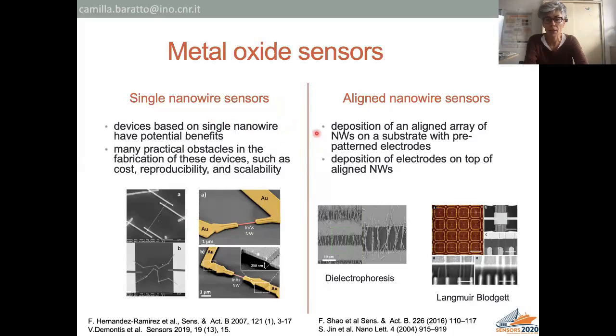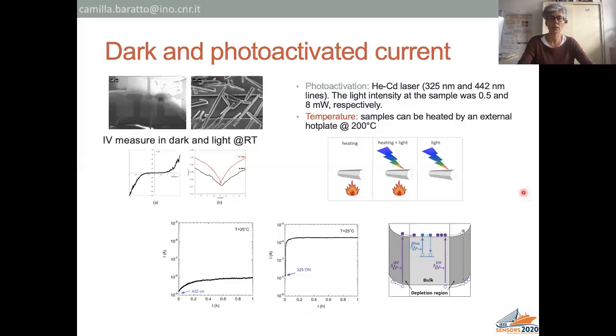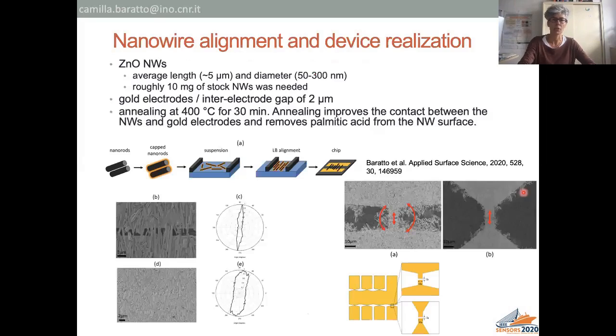And in literature, it has been proposed to use many nanowires that are similar one to each other, aligned between contacts. And different techniques were used to align the nanowires between the contacts, like, for example, the application of an electric field in dielectrophoresis. So several nanowires can be aligned over two cross contacts. Or another approach is to align the nanowires over a substrate and then to deposit them over the contacts.